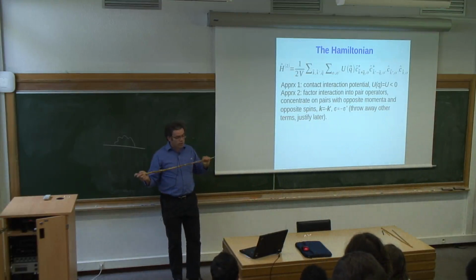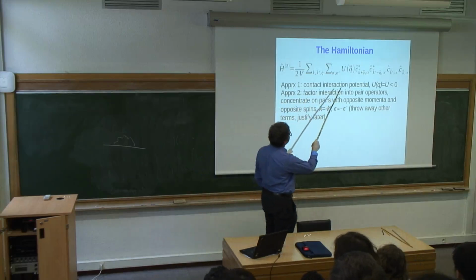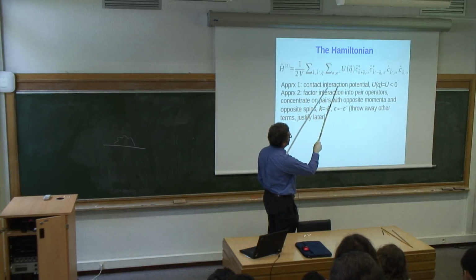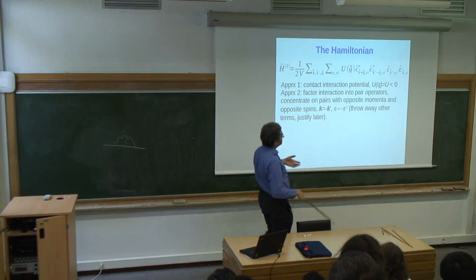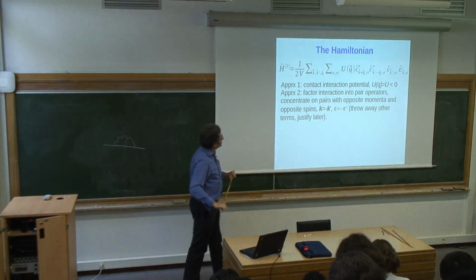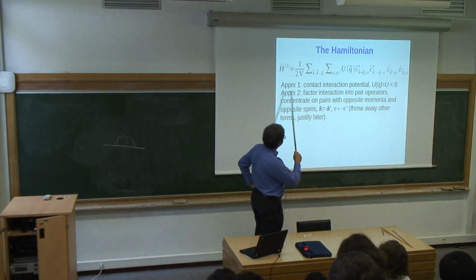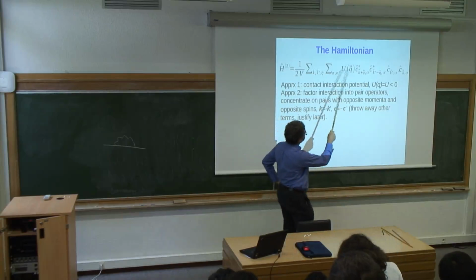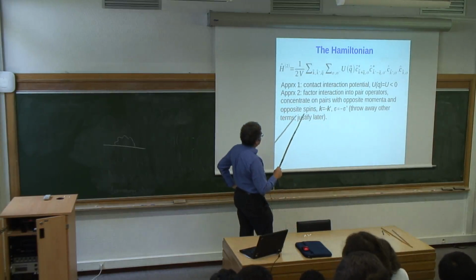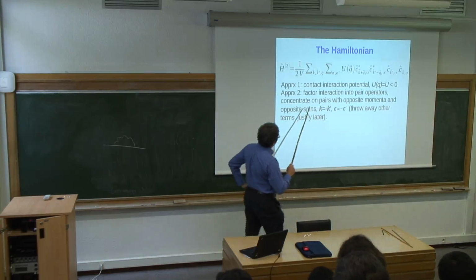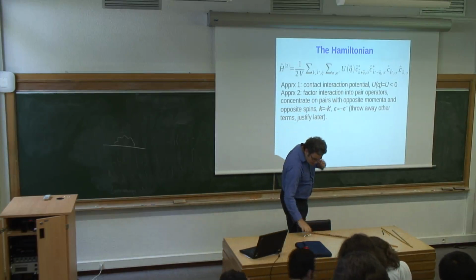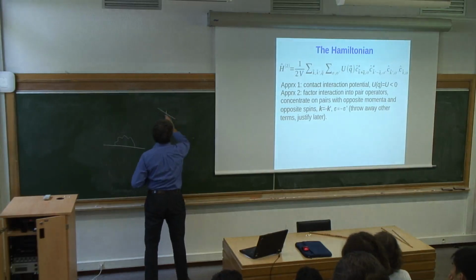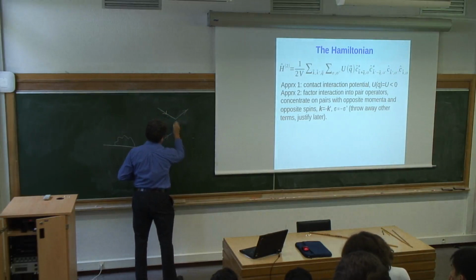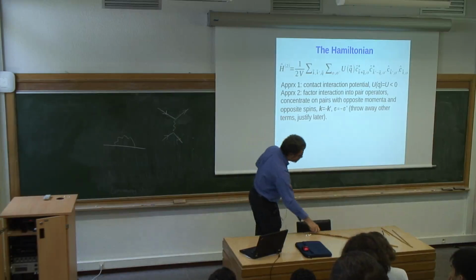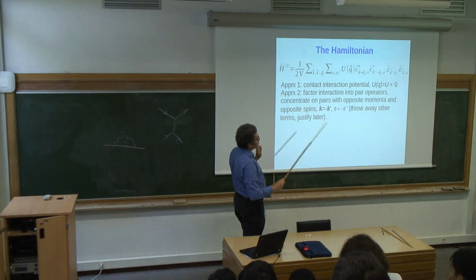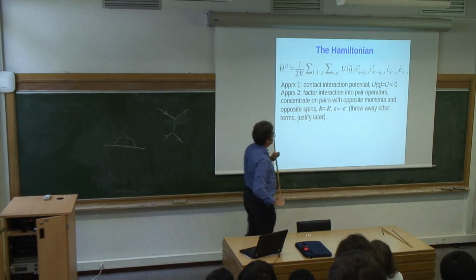All right. So you start with a Hamiltonian, which is two particle interaction, and so this is somehow a model Hamiltonian in which phonons don't appear explicitly. This interaction represents an effective interaction due to this phonon-mediated effective interaction, which is attraction. And we'll make approximation 1: replace it just by a negative constant, forget about spatial dependence, spatial dispersion, etc. And then approximation 2 is that one should focus on the terms. So this is basically two particle scattering, where you have particle 1, particle 2 coming together and then interacting via this potential. And all quantum numbers in principle are allowed, which are not forbidden by spin conservation, momentum conservation, etc.